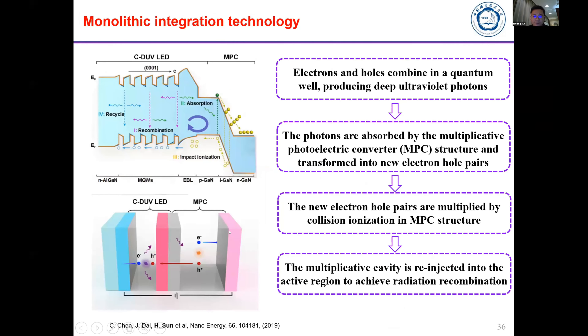Lastly I want to discuss device structure optimization. Normally light exits from the back sapphire side, but the p-GaN side — which has a smaller band gap — can absorb the UV light. What we have done is introduce a photo detector to absorb the wasted photons coming from this side, then regenerate electrical carriers and re-inject them into the active region to improve the light extraction efficiency.